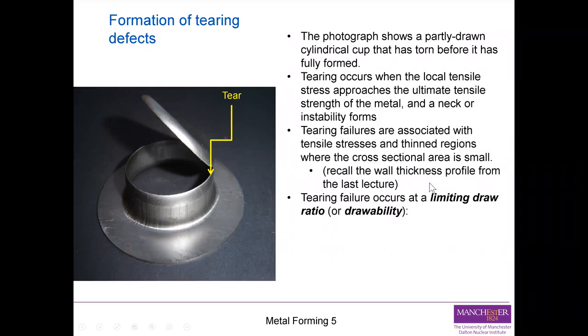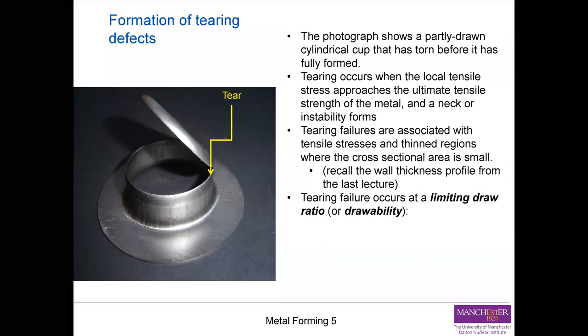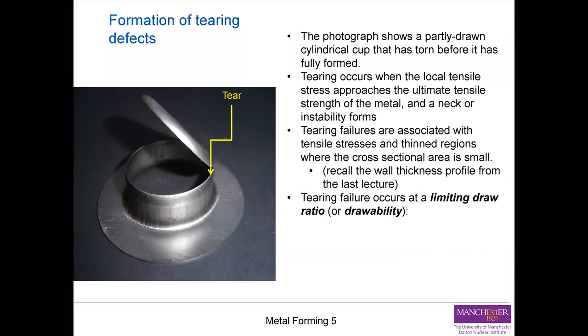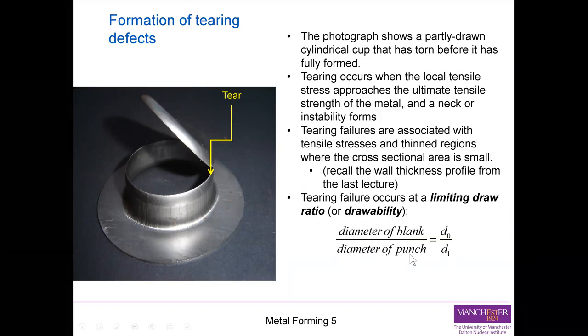And we can recall the wall thickness profile from the last lecture. There is a very important piece of information stated in this slide, and this is that there is a limit. Tearing failure occurs at the limiting draw ratio, which is called drawability. And this is the definition: the diameter of the blank over the diameter of the punch, D0 over D1. This is the limit of how much draw you can do before the end comes off, as we said.